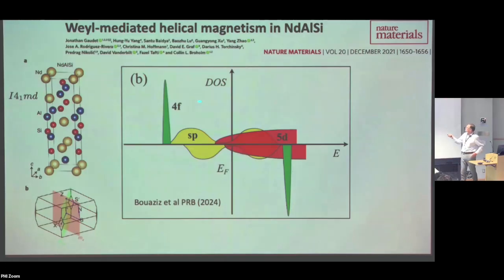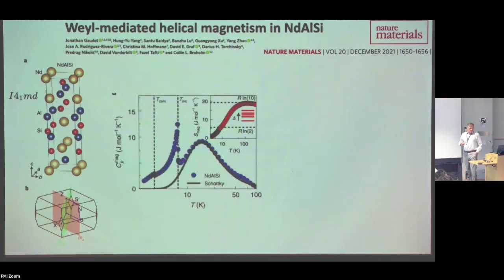This can be an emphasis because the 4f electrons in this material are not at all involved with the transport properties. They're really very far from the chemical potential. And so we can really think of it in the normal RKKY mechanism where the f electron is causing some kind of a Friedel oscillation in the spin density, which is then impacting another 4f electron at a distant site. And so we should expect some kind of oscillatory nature of the exchange interactions that we should be able to detect in this material. All right, so let me show a couple of the thermodynamic properties. That's the specific heat, just the magnetic part of the specific heat.